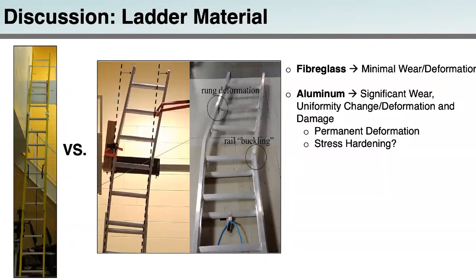In contrast, the aluminum ladder sustained large amounts of wear, uniformity, change, and deformation and damage across the conditions tested. In general, the rightward horizontal force direction conditions were most destructive to the aluminum ladder, resulting in significant deformation to the aluminum side rails. This deformation ultimately led to the side rails buckling and ladder failure. The deformation in the aluminum ladders primarily occurred above the point where the ladder was tied off. This tie-off location acted as a fulcrum or pivot point, and the ladder was generally unaffected below that point.